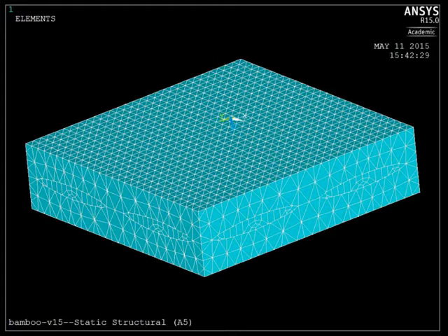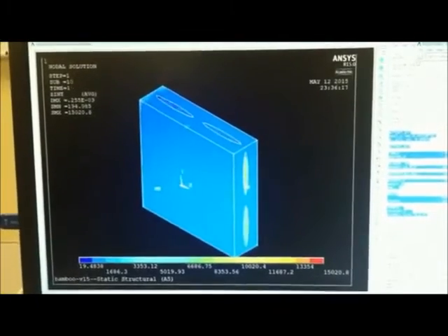The model was constrained to validate physical values by using periodic boundary conditions. The boundary conditions applied also allowed for the representation of a full sheet of weave by constraining each face to have equal values to the opposite side, so they may be repeated. This is a simulation of the tensile test performed. Notice the higher stress intensity within the fibers as well as the circular stress intensities arising on the closest face. The circular stress intensities represent where a transverse fiber is running over a longitudinal fiber subjected to the tensile stress.